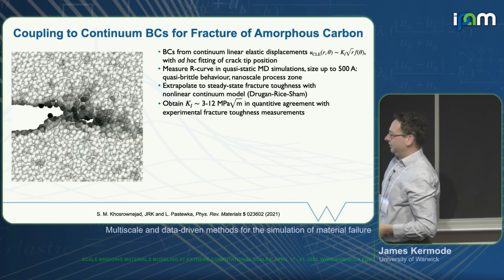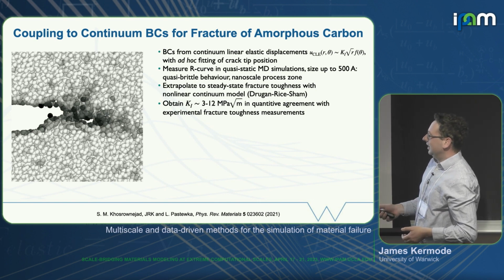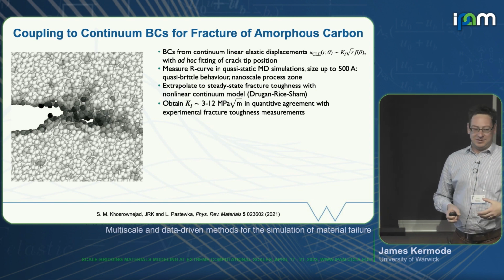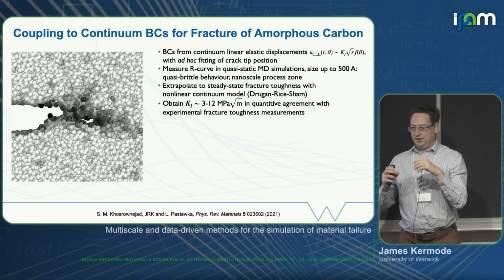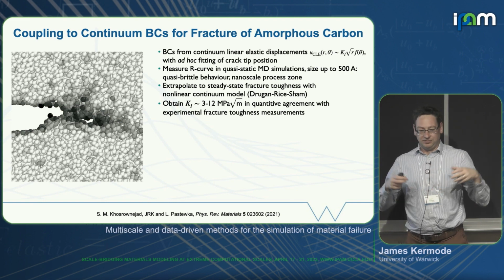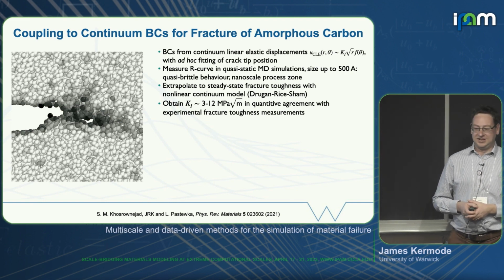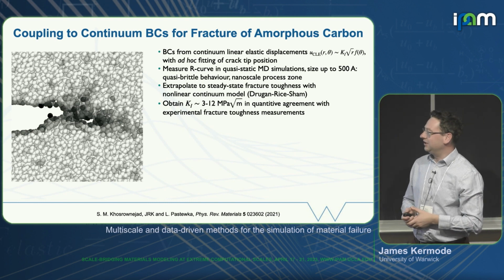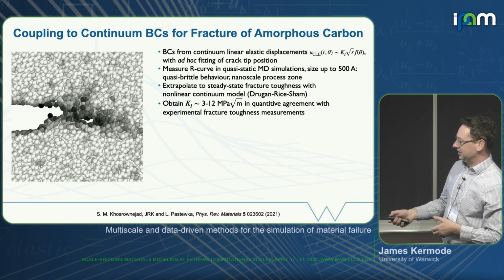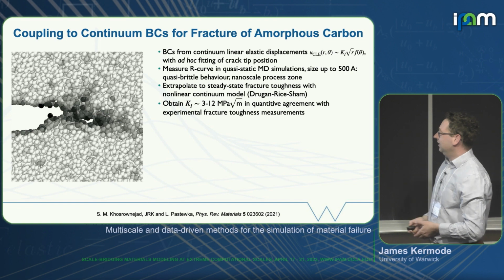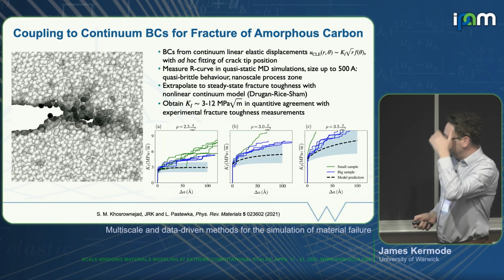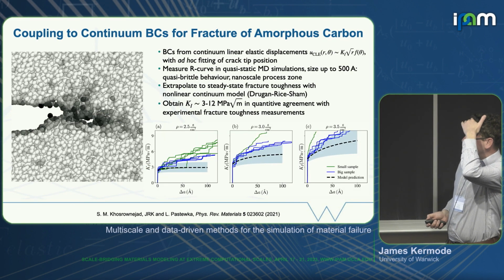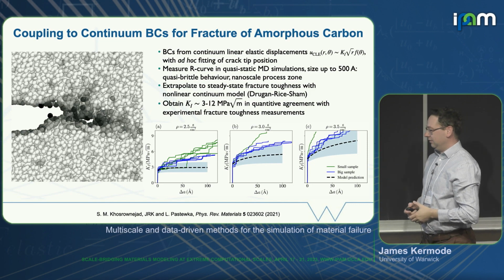If you look at a zoom in of the crack tip here, you can see we've got a kind of quasi-brittle behavior. So it's like a ductile material. We see formation of voids, coalescence, and so on, but right down on the nanoscale where we can investigate it with atomistic modeling. So it's quite a nice playground. This process zone is on the nanoscale. And we can actually, again, make fracture toughness predictions in good agreement with experiment.